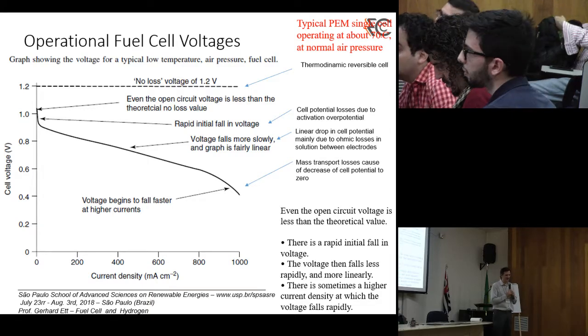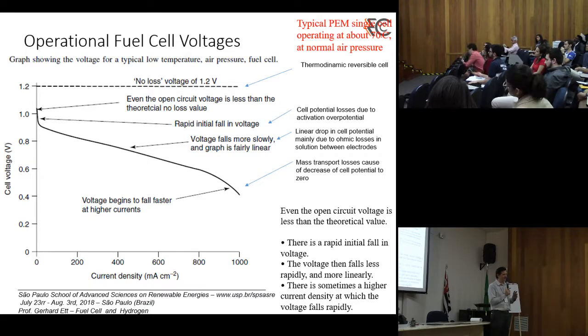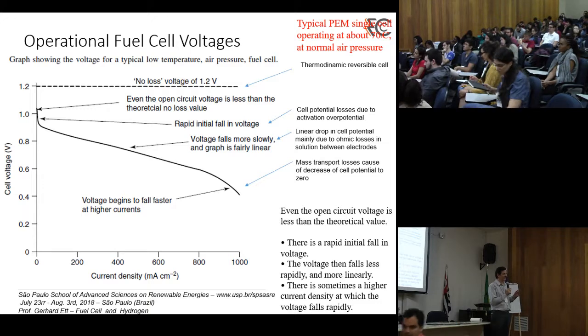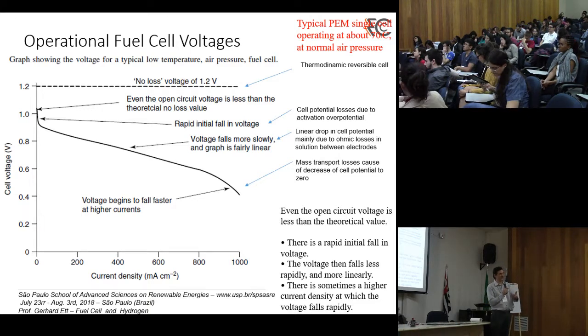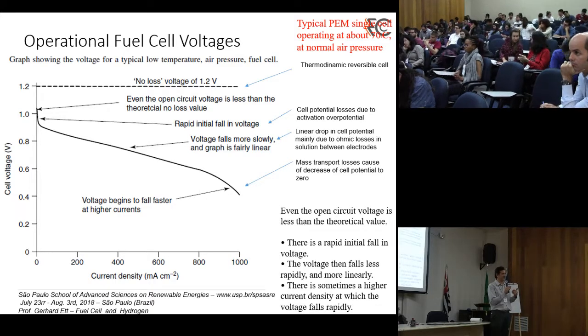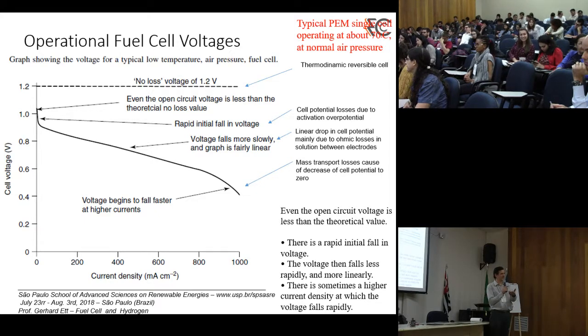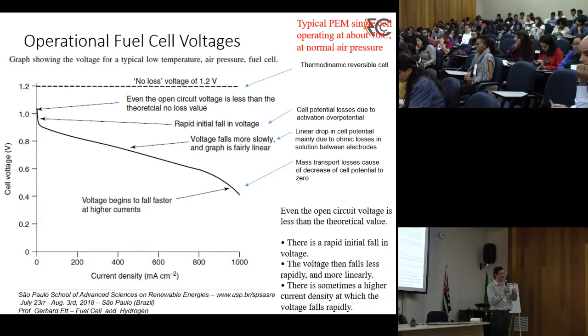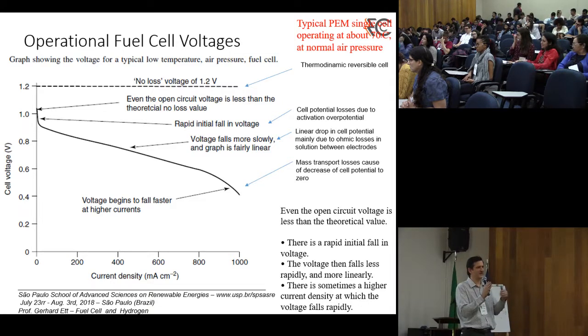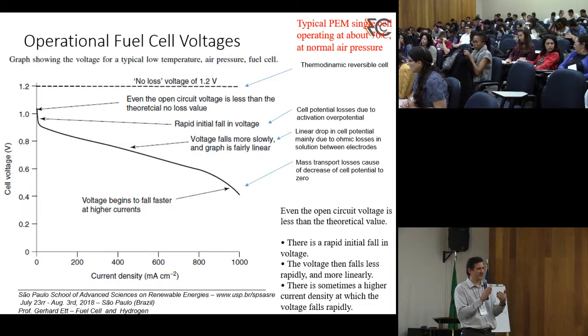Okay. Yeah, high temperature is good to reduce activation, but there is a limit. For example, in the PEM fuel cell, you can increase the temperature, but normally the temperature used is 65 degrees. If you increase more than 80 degrees, you will have problems of diffusion in the cell. So there is a limit on the temperature at which a PEM fuel cell can operate. With the solid oxide fuel cell, we have the same problem, but the activation is very low because you work at 1,000 degrees, 800 degrees. Every stack has some limit, and you need to take care of the limit of the stack.